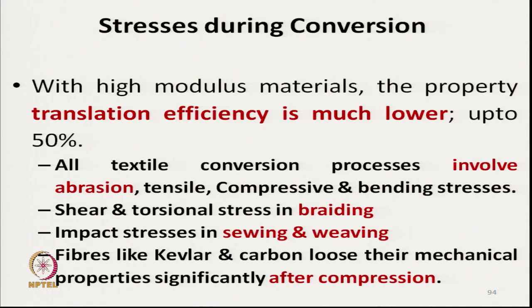Also, most textile conversion processes involve abrasion, tensile, compression, and bending stresses, which effectively damage the textile reinforcing material. Shear and torsional stress is exerted during braiding which damages the yarns or fibers. Impact stresses in sewing and weaving also cause damage — fibers like Kevlar and carbon lose their properties significantly during compression or bending.